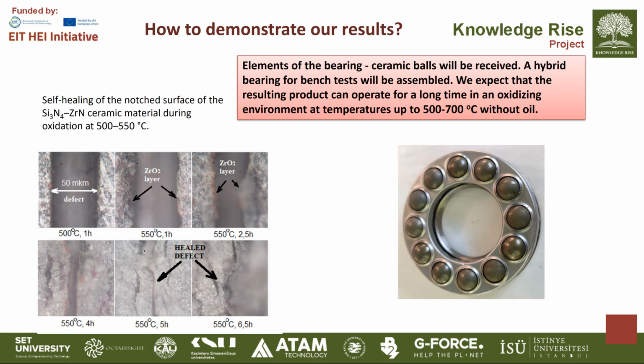The study and demonstration of self-healing effect for these ceramic composites highlight a transformative approach in advanced materials engineering. Through the controlled oxidation of zirconium nitride particles, cracks could be autonomously filled by zirconium dioxide, as I say, leading to complete restoration of surface integrity at relatively low temperatures. This phenomenon enabled us to develop a class of new smart self-sustaining ceramic materials suitable for high-performance applications. When applied in a hybrid bearing system, such material offers unprecedented resistance to wear, oxidation, and mechanical degradation, allowing continuous operation at elevated temperature without lubrication.